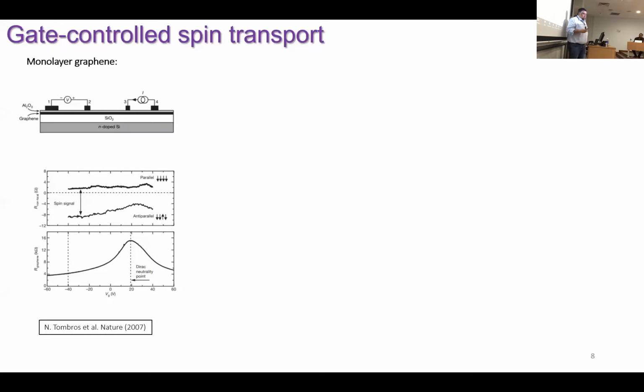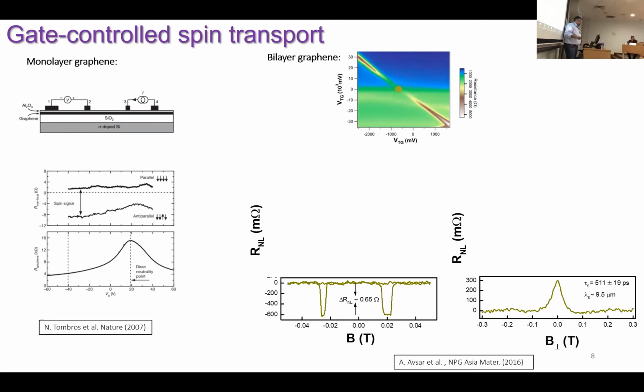But for me, one of the most exciting parts of 2D materials is the gate tunability. These are extremely thin materials, and if you apply an electric field, you can change something. But unfortunately, you cannot change much with graphene because it's a semi-metal. As you can see here, the resistance of graphene changes just a few times with the gate voltage, and indeed, the spin current also shows almost no change with the application of the gate voltage. If you think about this beyond the CMOS era, you also need gate tunability so that you have an extra knob. So this is something that we tried with bilayer graphene.